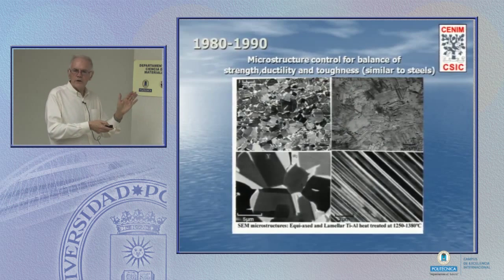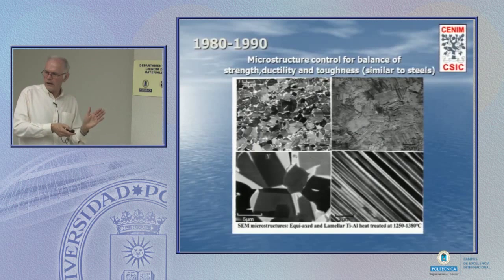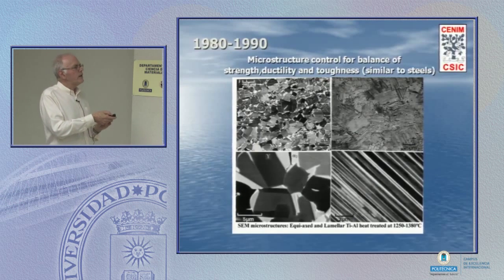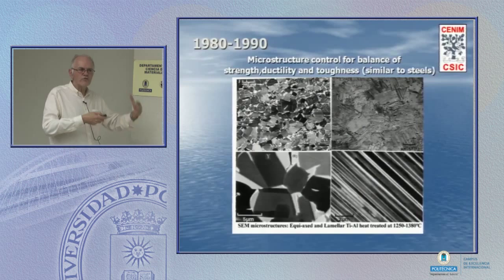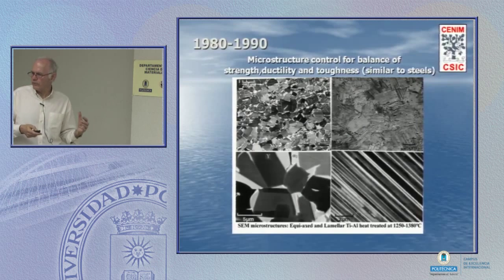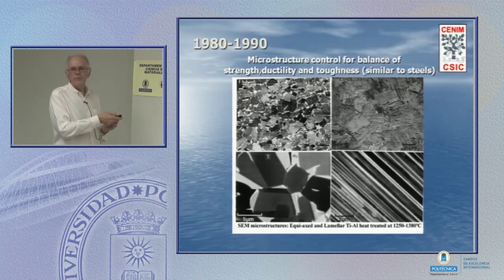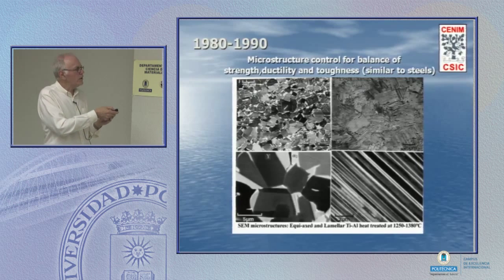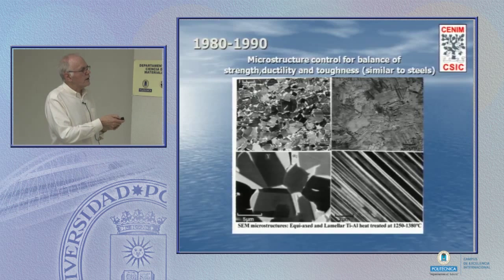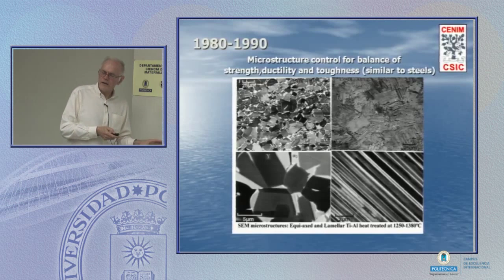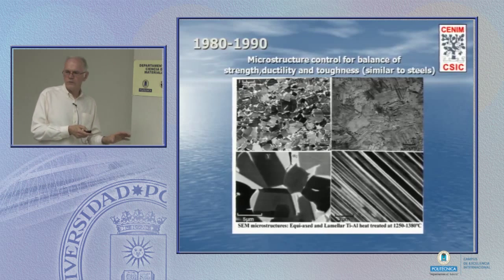This is one of these alpha-gamma alloys. Simply by heat treating the final object after machining, after forming, after everything you want, we heat it up to high temperature, cool it down relatively quickly, or cool it down rather slowly. Here what we've got are grains, something like 25 microns in size. Within them there's a lamellar structure. It's exactly the equivalent of pearlite in steels.